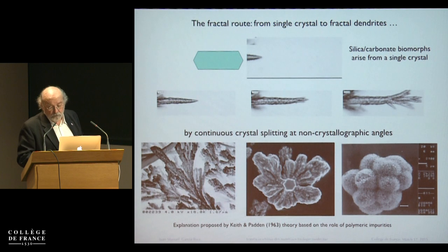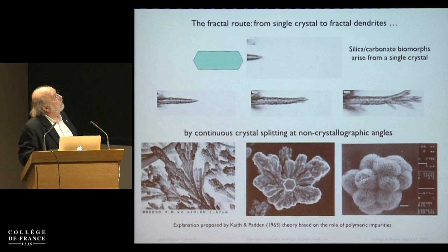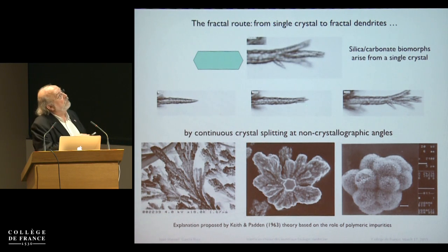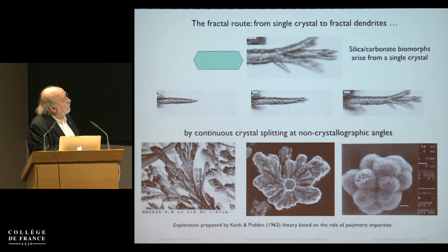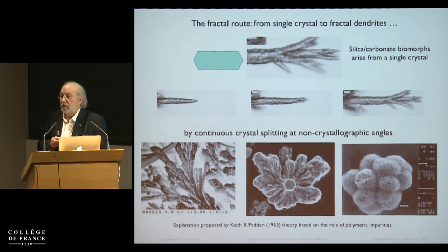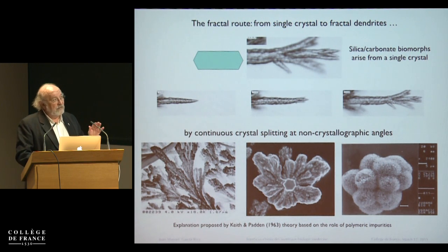This is the mechanism in which you can see here the pyramidal faces of the barium carbonate. So you have the prismatic face here, the hexagonal prismatic prism, and this is the hexagonal bipyramid, okay? And then when the crystal grows, it starts to split the tip, okay? And you can see there is non-crystallographic branching. And this non-crystallographic branching is the one that produces this fractal structure, cauliflower-like fractal structure that from outside looks globular, but inside has this crystallographic fractal structure.